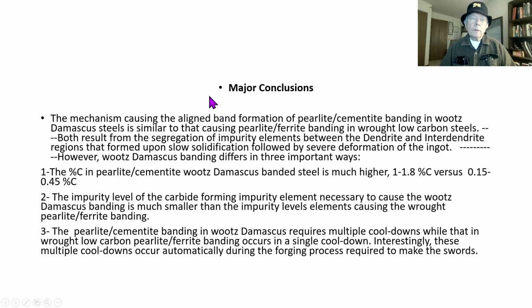Okay, so now I'm going to conclude. The mechanism causing the aligned band formation of pearlite banding, cementite banding in Wootz Damascus blades is similar to that causing pearlite ferrite banding in wrought low carbon steels. Both result from the segregation of the impurity elements between the dendrites and the interdendritic regions formed when the steel solidified slowly, followed by severe deformation of the ingot.